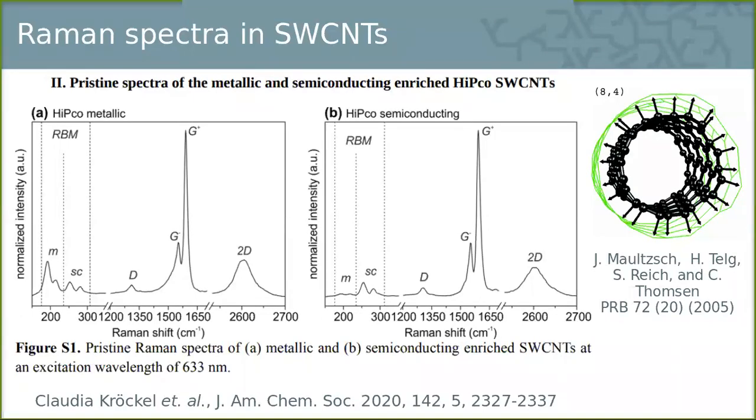So basically, when you take a carbon nanotube, you will see a black material. But if you use a Raman spectrometer to analyze single wall carbon nanotubes, you will see that in the region between 100 and 300 cm^-1, you will find these very intense and characteristic peaks.